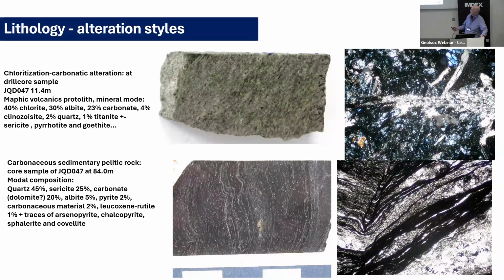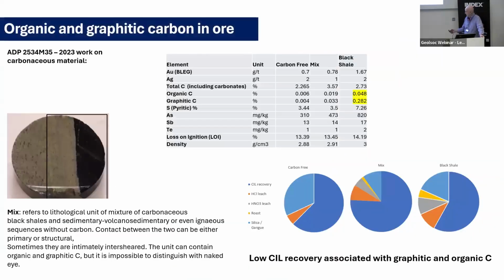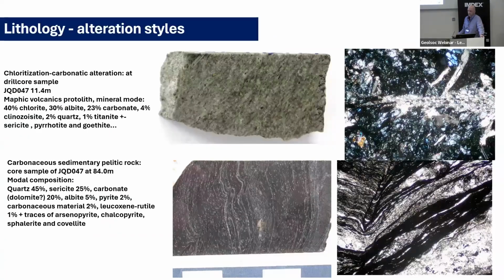One of the things I would like to draw your attention to is this carbonaceous material. It says 2%. 2% of carbon in a rock, due to its density differential, takes it up to about 5% by volume. And the surface area of carbon, especially in a grinding circuit, can be made extremely fine. Natural carbon has the ability to absorb between 5,000 and 10,000 parts per million gold in a cyanide solution, which goes straight out to tailings. So you can be very clever with how you process this material, but if you haven't taken this into account, then you can have trouble.